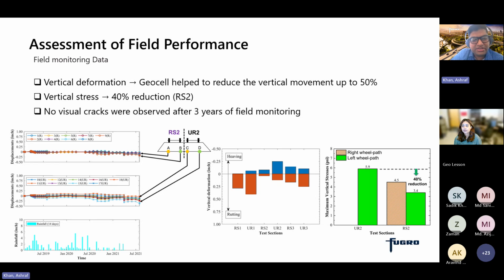Not only the sensor data, we took regular surveys to check the rutting or the visual cracks on the road surface. And after the 3 years of construction, we did not record any visual cracks on the surface, which means the use of Geocell helped to reduce the bottom-up cracking.